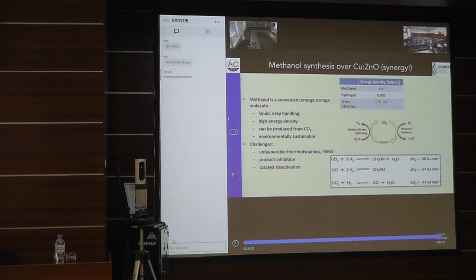The important thing to notice, which is also the only real challenge in this kind of chemistry, is that this is an equilibrium-based reaction that has three molecules in it, CO2, CO, and methanol. And all three form an equilibrium, and that means it is, under circumstances, not so easy to control the selectivity such that you either do reverse water-gas shift reaction or methanol synthesis. You cannot escape this problem.